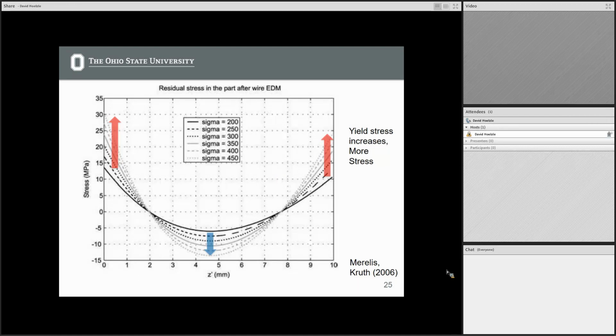So I think that is interesting with respect to being able to vary the build plate thickness you have based on what you want to be printing. To me, it was surprising you have so many different parameters that you could be varying when you design your AM process to be able to counteract some of these negative effects and begin to reduce that residual stress. And so it's not just that you print it and anneal it and you have a part. There are specific things you can tune in your process itself, anything from scanning strategy to build plate thickness, to be able to actually begin to mitigate some of these effects.